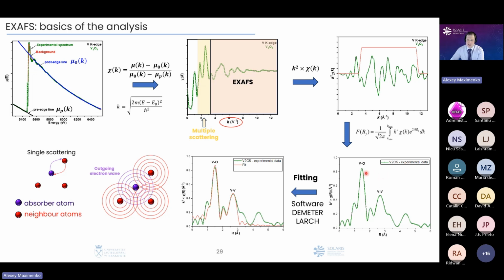Main amplitudes, and investigation of the position of these main amplitudes, their intensity actually corresponds to the interactions. It means interaction between our absorbing atom and the neighbors. For example, here the closest neighbor for vanadium pentoxide was oxygen, definitely. So it was an interaction between vanadium and oxygen. The next coordination shell, the next interaction which we have in our material, was vanadium-vanadium.